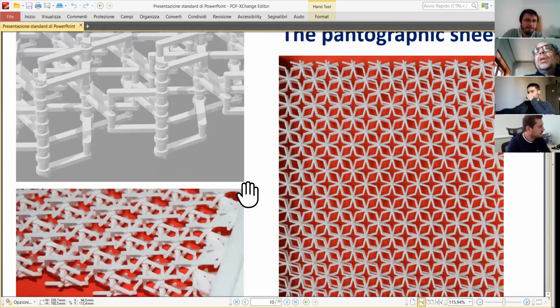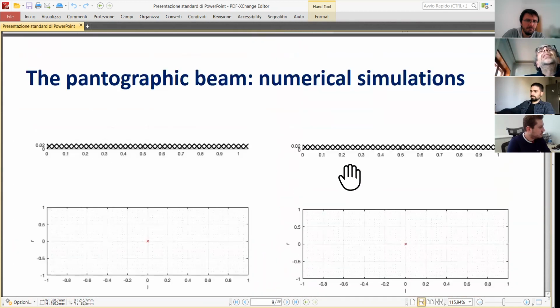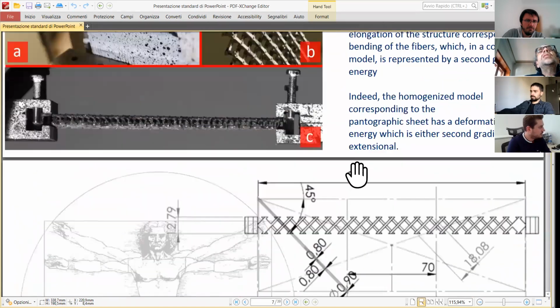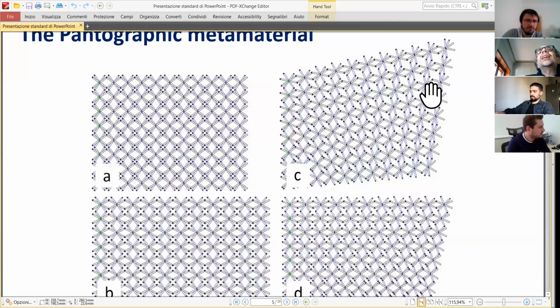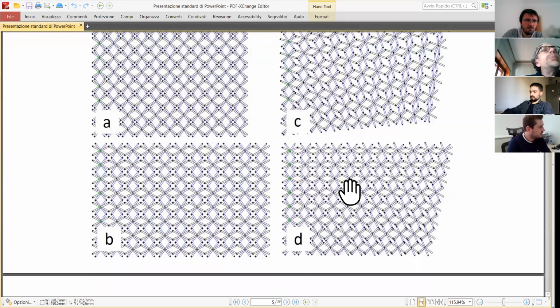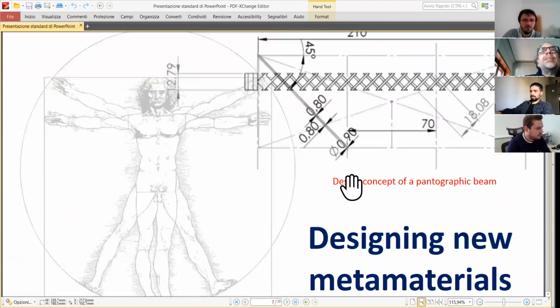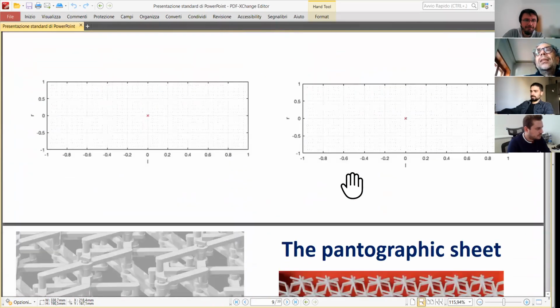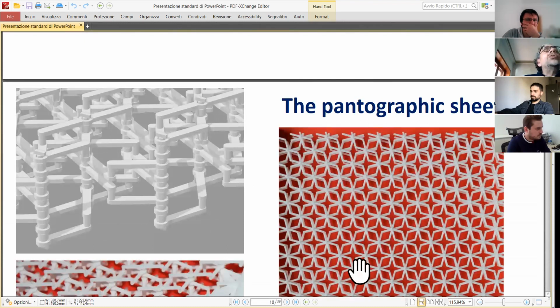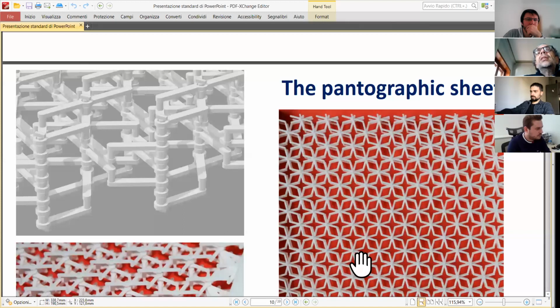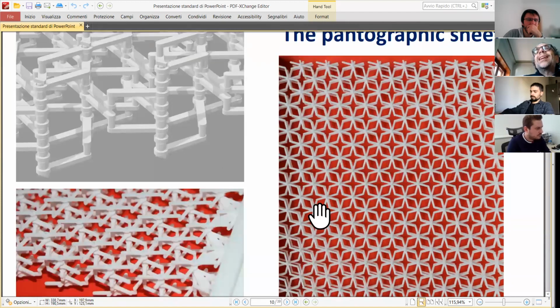mechanical engineering. And we could print the specimen, this is the picture of the specimen, and we could prove experimentally that the behavior which I described to you before, this one, with this kind of deformation energies, which are associated with a very low deformation energy, are feasible experimentally. So this material, this pantographic sheet, can undergo large deformations remaining in the elastic regime. It starts being broken when one of these pivots undergoes a strong shear deformation and it breaks.